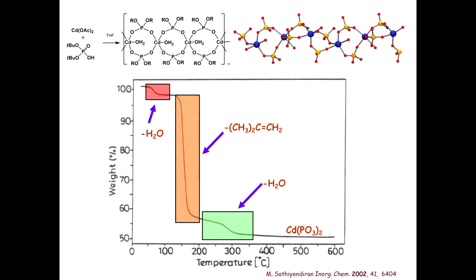Yeah, I'll just show one example, a very early example from my group, the cadmium phosphate polymer, which is a one-dimensional polymer. As you can see, the whole backbone is inorganic. The only organic part is the R group sitting on the top, that is the tertiary butyl group. So the coordinated water leaves at a fairly low temperature, about 70 to 80 degrees centigrade.